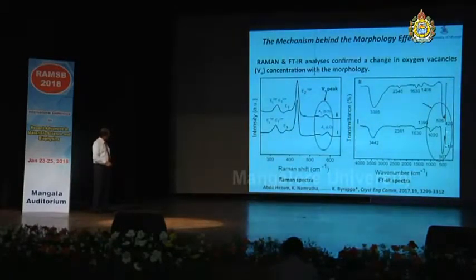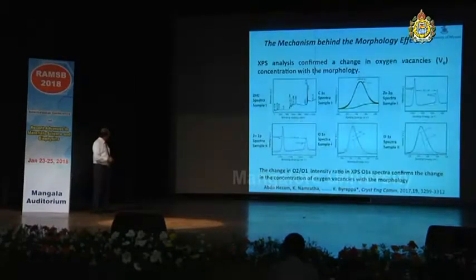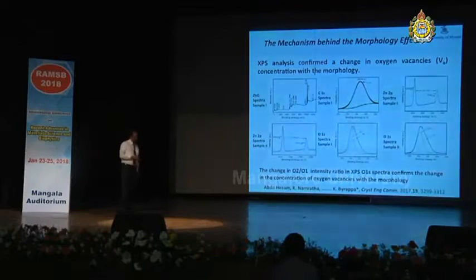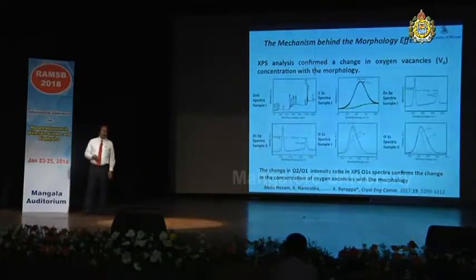You can see the splitting of the bands. And we have also carried out the XPS analysis to confirm a change in the oxygen vacancies with the change in morphology, and this has been very well accepted, in fact, and we even discussed this with Professor Challapati Jagadish. And the change in this oxygen vacancies intensity ratio in XPS